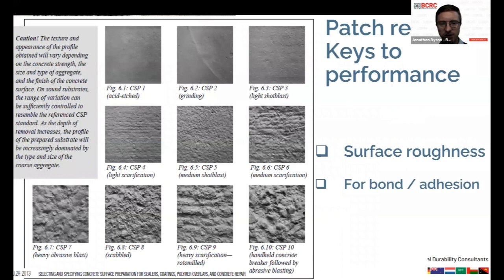So once you've broken out the concrete, the next step is to make sure you achieve a good concrete surface profile. So surface roughness of the substrate, essentially. That's important to get adequate bond and adhesion of the patch repair material or of the overlay that you're applying. So not just for cementitious patch repair materials, but it can also be important for things like protective coatings. Depending on what you're talking about, you might want a medium level concrete surface profile, or sometimes you might want a high surface profile. And the other thing is that the rougher the surface profile, the more shear interlock you're going to have between the patch repair material and the parent concrete. So the more it can act as a monolithic structure or element.